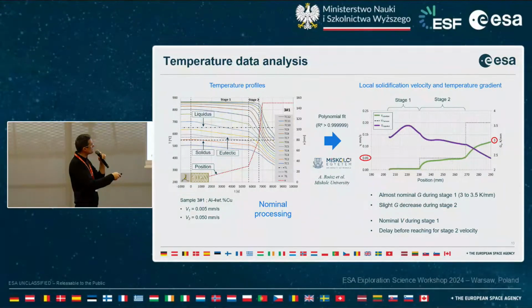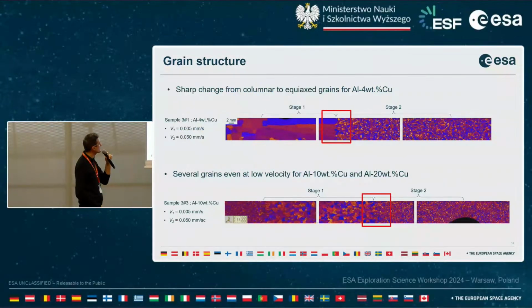And what is interesting is that there is a transient stage before the growth front, before the isotherms reach the velocity set point. And this is something that we will see back in the grain structure characterization. So this transient stage will have an effect on the grain structure. And this is what we see here for 2 alloys, aluminum 4 weight% copper, and here aluminum 10 weight% copper.